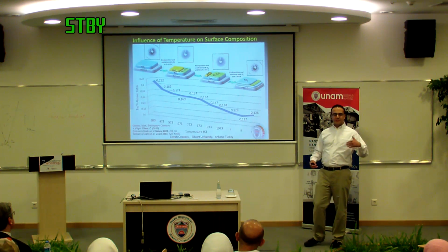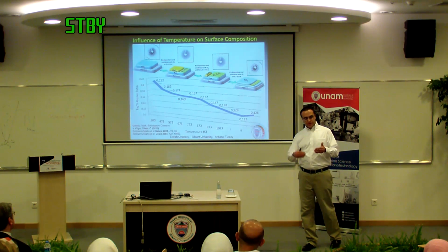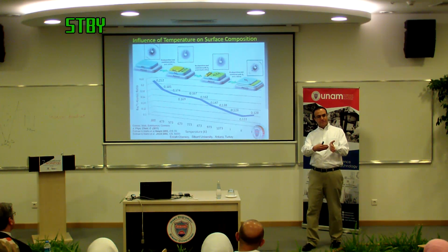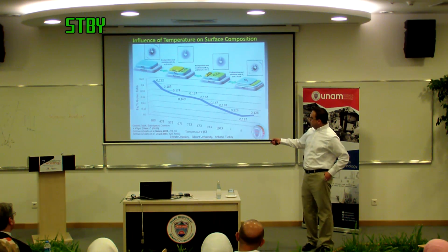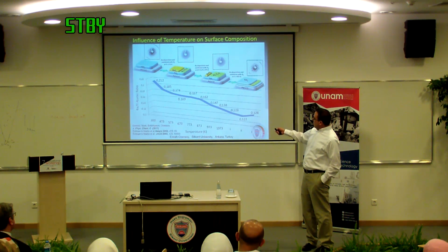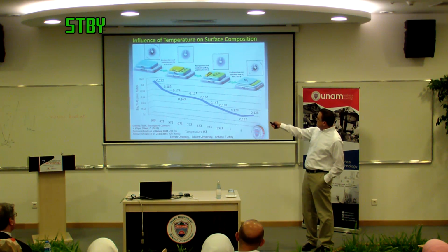And you can say it's just desorbing, evaporating. It's not, because we just put a mass spec, we don't see the barium desorbing. So barium is going somewhere, it's actually going below the surface, into the bulk. And if you heat it high enough, the barium level goes so much down, and the diffraction pattern becomes identical to